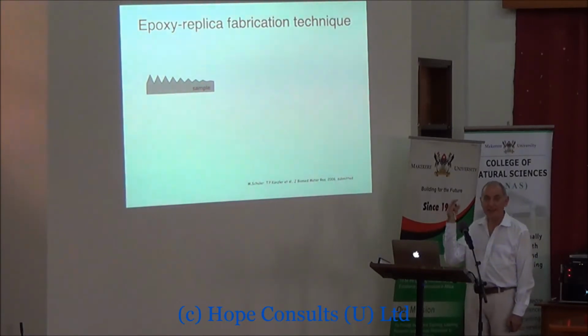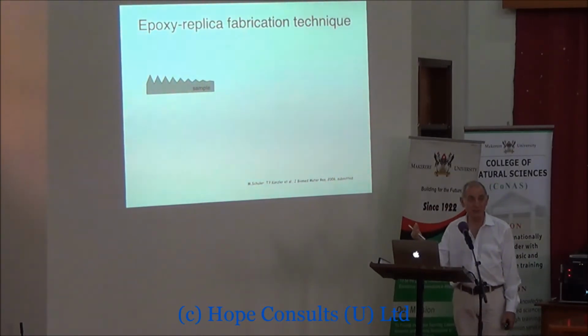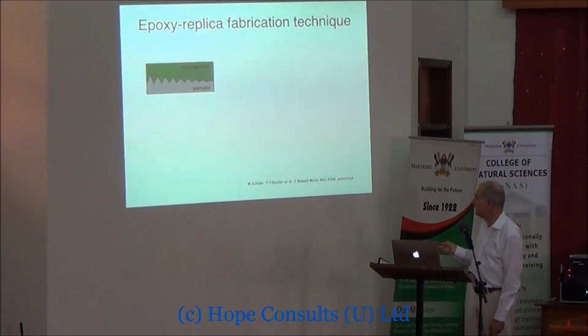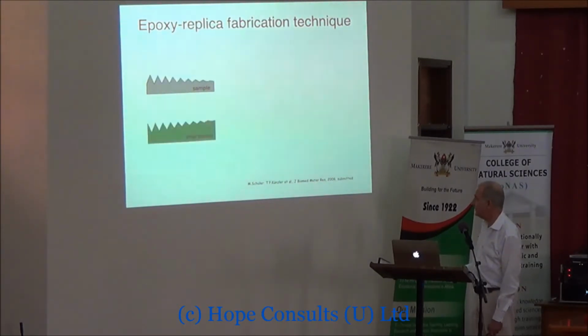And what I just described to you, sandblasting stuff, you can't make the same surface twice, obviously, if you sandblast it. And so what we decided to do is make a master by sandblasting and the chemical polishing technique, and then use that as a master to produce identical replicas. And the way we did that is we take the kind of stuff that people use to take impressions of teeth. It's a polymer called polyvinyl siloxane. And we use that to make a negative of the surface. And so now we have a negative. And then we used epoxy resin to make a positive from that negative. And then we turn it upside down once we've separated it from the negative.